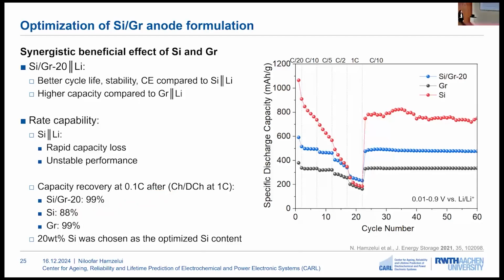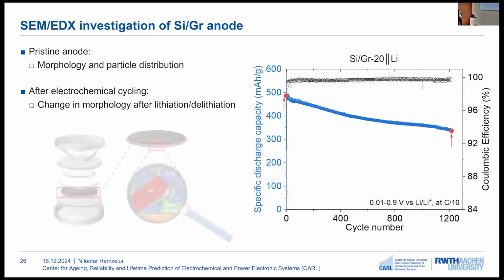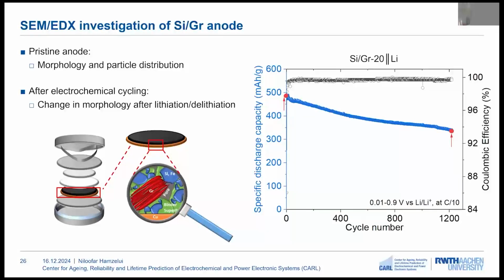Based on the electrochemical measurements which have been shown so far, the silicon graphite electrode with 20 weight% silicon was chosen as the optimized silicon content in this work. The morphology and structure of the silicon particles of the silicon electrode was also investigated using SEM-EDX analysis. Firstly, the pristine electrode was investigated to see the structure and the morphology of the electrode before cycling. And after cycling, the cells were disassembled, and the anode was investigated using SEM and EDX to see the structural changes which happen after electrochemical cycling.